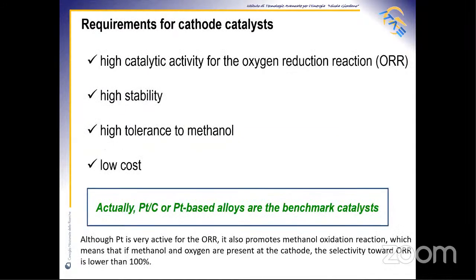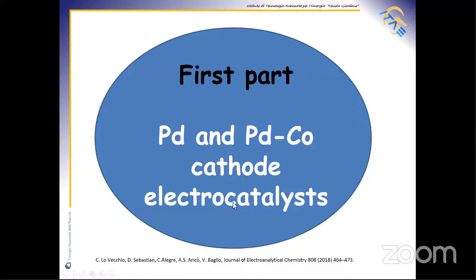Next generation cathode catalysts for direct methanol fuel cells must have high catalytic activity for the oxygen reduction reaction, a lower cost than benchmark platinum catalyst, high stability, and high tolerance to permeated methanol. Thus, a complete replacement of platinum-based catalyst characterized by low methanol tolerance was first explored by our group with palladium electrocatalyst and palladium-cobalt alloys.